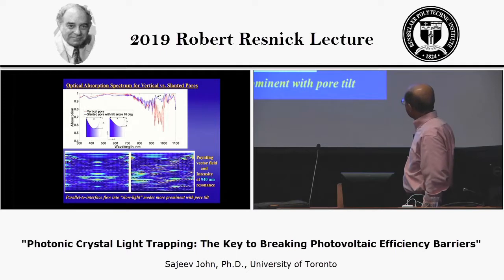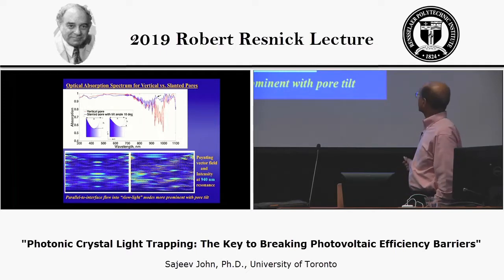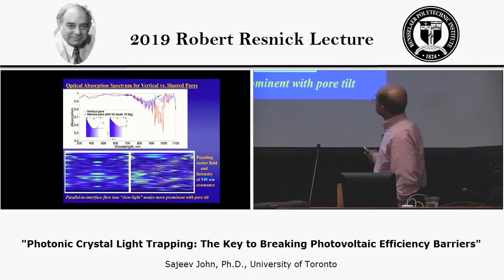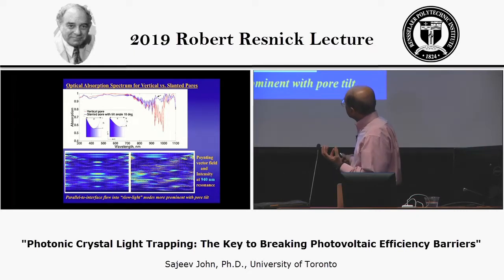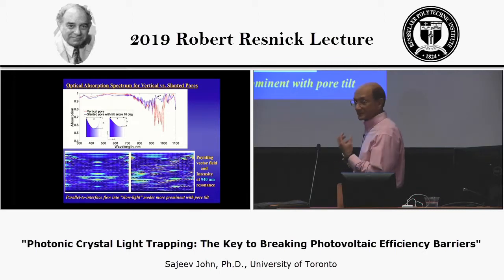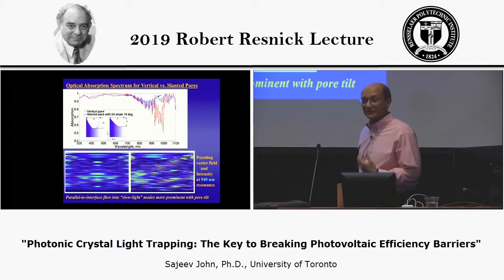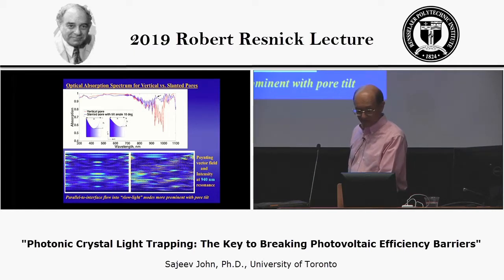This is a particular resonance at 940 nanometers, and you can see this type of parallel to interface flow of the Poynting vector. There's some vorticity in the Poynting vector as well, creating this long dwell time in the structure. This is the outline of the parabolic pore seen here. And in this tilted pore structure, this is more evident than in the vertical pore structure. So the physics that we're talking about seems to be evident in these actual experimental structures.